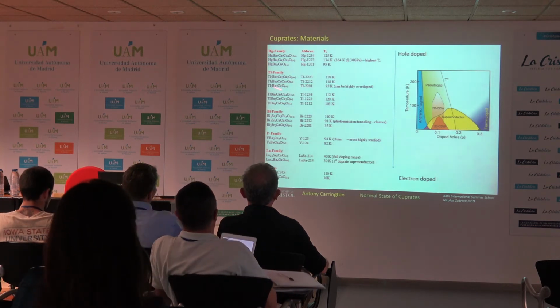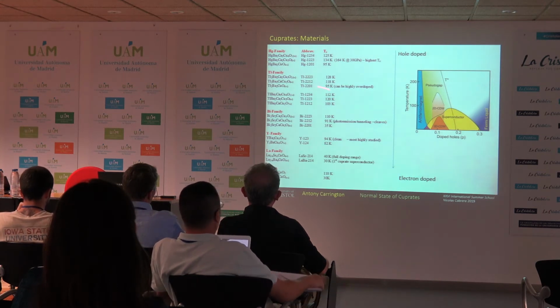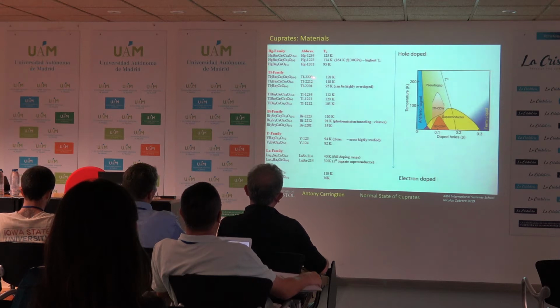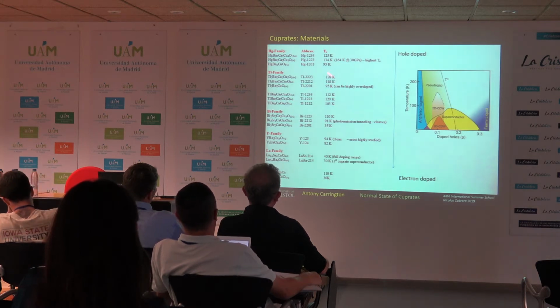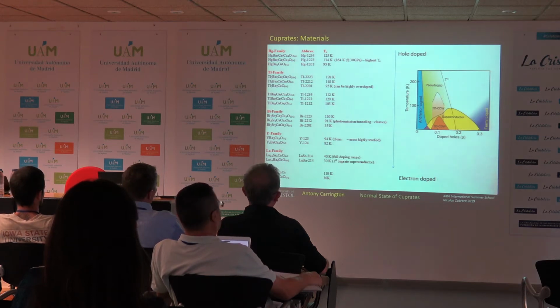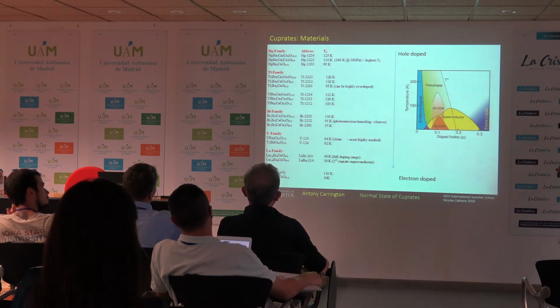So for example, if we look at the thallium family, we've got thallium 2201, which has a single copper oxide layer. The next one up's got 2, and the next one up's got 3. Generally, the Tc increases a little bit as you go to more and more layers, but it's roughly always about 100 Kelvin, plus or minus 20–30%. So depending on what your experiment is, you pick one of these as your favourite.